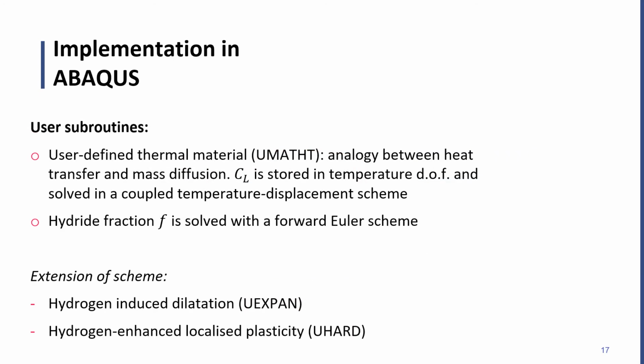The implementation of both hydrogen transport and hydride formation is performed in a user subroutine in Abaqus, and we exploit the analogy with the heat transfer equation, so we use a UMATHT, and the concentration in lattice sites is solved using the temperature degree of freedom. However, for the hydride volume fraction, we cannot use this degree of freedom, and we just implement a forward Euler scheme. It is important also to note that we will not discuss dilatation and hydrogen-modified plasticity, but these are critical phenomena for embrittlement, and we have also implemented the corresponding equations using a user expansion and a user hardening in Abaqus. So in future research, we are going to also discuss all of these processes.